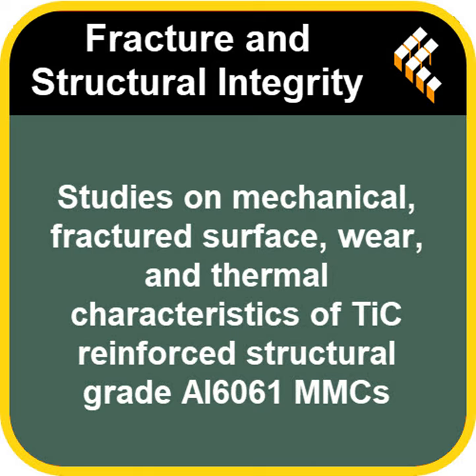It's not just about adding a hard particle passively resisting wear. It's about how that particle interacts dynamically to distribute load, reduce internal friction, and even actively form a protective interface. It's quite sophisticated. And no, the trend didn't hold past 9%, just like with tensile strength and hardness. Let me guess. Higher wear loss at 12%.